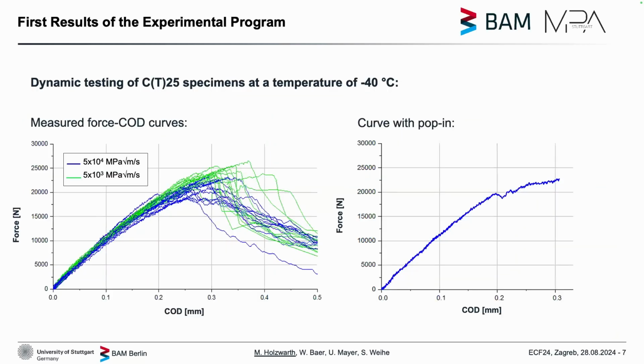We used a machine which can go as fast as 10 meters per second and up to a load of 100 kilonewton. We used high-speed cameras at 100,000 FPS to measure the COD of the specimen. And for the force measurement, we used, for the slower tests, piezo load cells. And for the faster tests, we used strain gauges. We tested at 2 different loading rates. One of the loading rates was 5 times 10 to the power of 3, and the other one was 5 times 10 to the power of 4. I will from now on reference those as the slower and the faster loading rate.